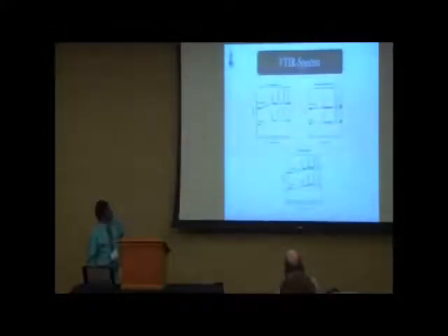So you can see, especially in herbaceous biochars, there is a C-N stretch, a C=O double bond stretch, a C-O single bond stretch, and an aromatic C-H vibrational band. Whereas in Ponderosa pine, it also has C-N and C-O and then aromatic C-H vibrations. So the chemical activation actually reduces the vibrational absorbance of these functional groups.